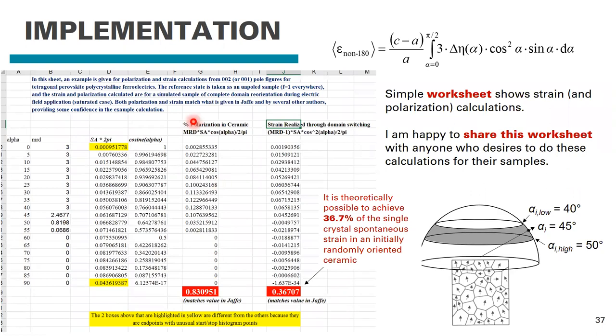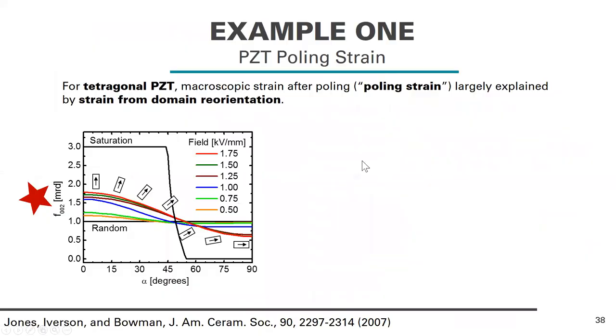And in fact, I've sent this spreadsheet to several of you on the call, as well as several others, as you were working through some of these calculations. And we know that this calculation is right, again, for one reason, because we calculated the maximum strain possible in a tetragonal perovskite crystal as 37% of the single crystal strain. And that matches values in Jaffe and some other similar publications. Okay, so I'm happy to share this with anyone that really wants to dive down an even deeper rabbit hole on this topic. But I'm going to come back up for a second. I don't want to dive any deeper down that rabbit hole.